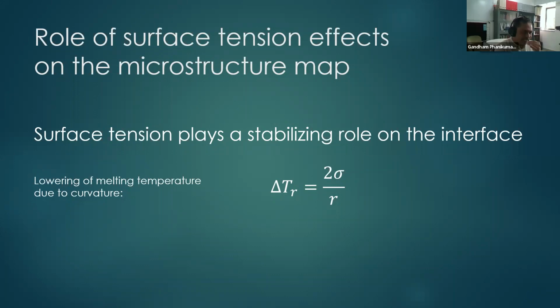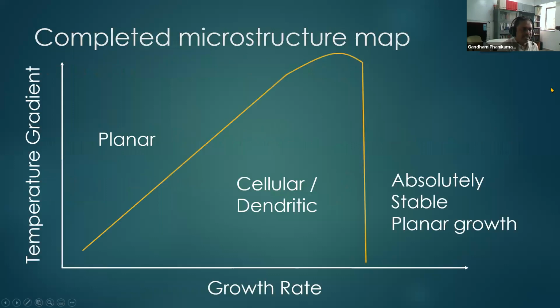So now these microstructural formations can also be suppressed, and that happens thanks to the surface tension effect. That is where the Mullins-Sekerka criterion tells you about the absolute stability. What it tells you is that if your growth rate is very fast, then you can get an absolutely stable growth, which means that there are no dendrites, there are no cells, the grains are growing as they are, and you get the same grain structure as what is in the base plate.